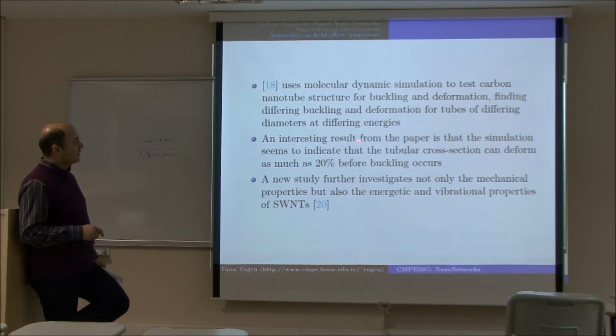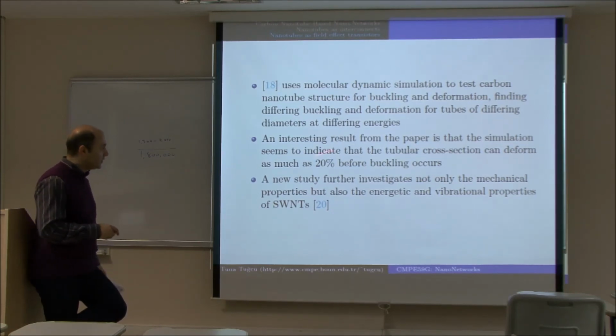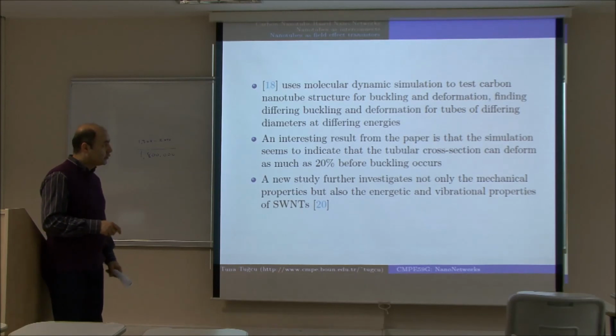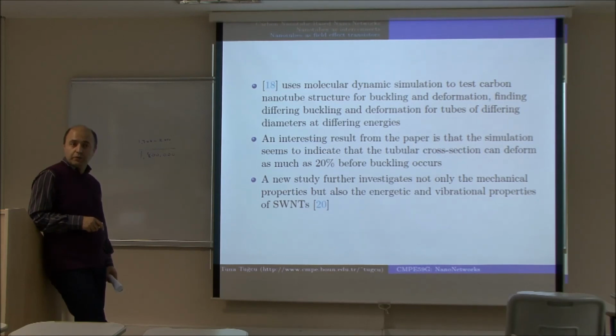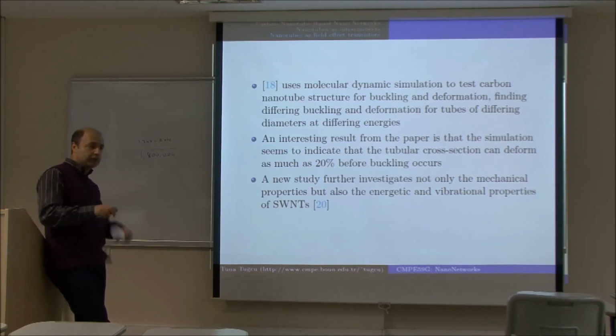An interesting result from this paper is that the simulation seems to indicate the tubular cross-section can deform as much as 20% before that buckling occurs. So it has some resistance to that force up to 20%. And after that, you have deformation.